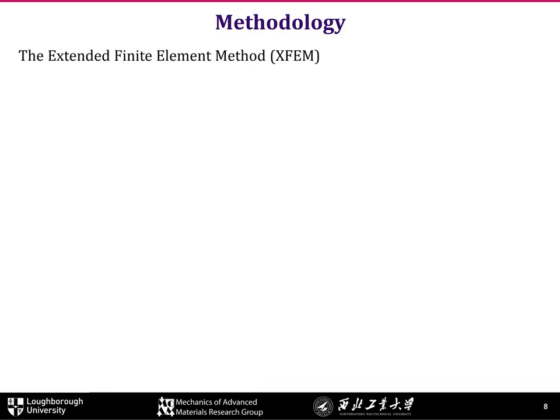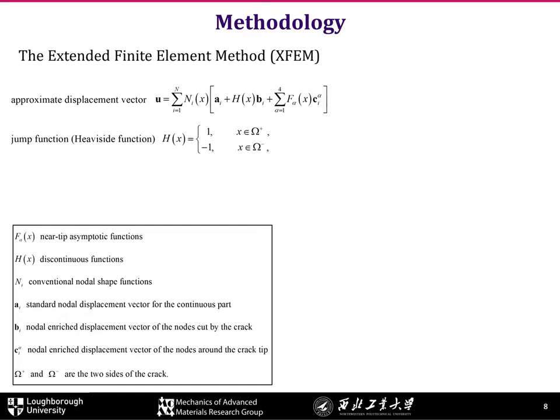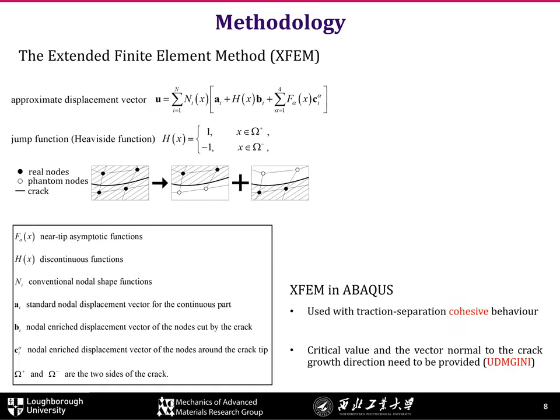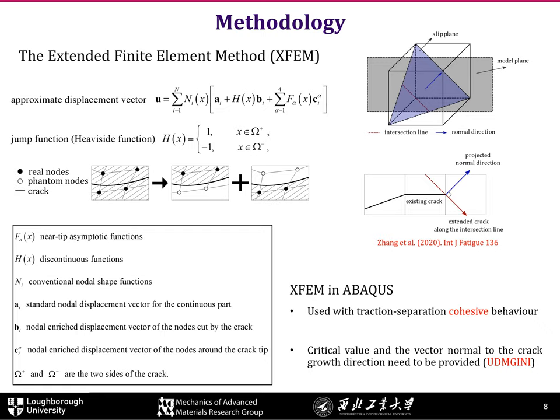The extended finite element method is designed to describe discontinuity in a mesh-independent way by introducing enrichment functions into standard FEM. N is the standard shape function, while h and f are enriched functions describing the displacement discontinuity and the crack-tip singularity. In Abaqus, it can be combined with cohesive behavior. Instead of function f, phantom nodes are introduced. Before damage, each phantom node and its corresponding real node are tied together. If an element is damaged, they separate and the element becomes two elements containing both real and phantom nodes. To simulate dynamic crack growth, a user-defined damage subroutine specifies the fracture parameter and the normal vector of the crack growth direction, provided according to the geometric relation of the slip plane.